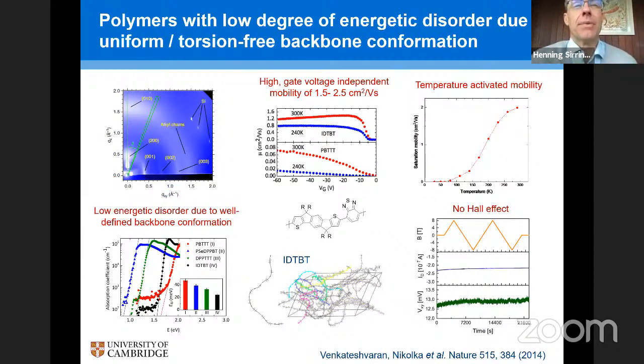And you're right, it does enhance the electronic coupling between neighboring molecular units significantly. And that's a good thing. But it also introduces a stronger sensitivity to residual disorder as soon as you have some torsional disorder, because in the solid state there's always some torsional disorder present. You become more sensitive to that because the units are coupled more strongly together, and so those two effects you have to balance. And so far we haven't really managed to develop these double bonded systems. I mean, they work very well, but not as well as we had hoped. And I think that's because you have to be even more careful about eliminating torsional disorder in these systems to achieve low degrees of energetic disorder. But it's certainly a very interesting future direction that we would like to explore more.